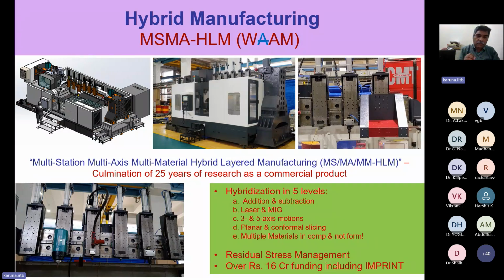So the energy beam basically creates the molten pool. Into that, the wires will plunge in and melt away. So if we have 4 wires, if we can have different compositions of the wires, then by controlling the wire velocity as well as the 5 axis motions, you have totally 9 degrees of freedom, using which you will be able to realize components which have the interior composition as well as porosity varying. So this is a very, very interesting aspect of our system.